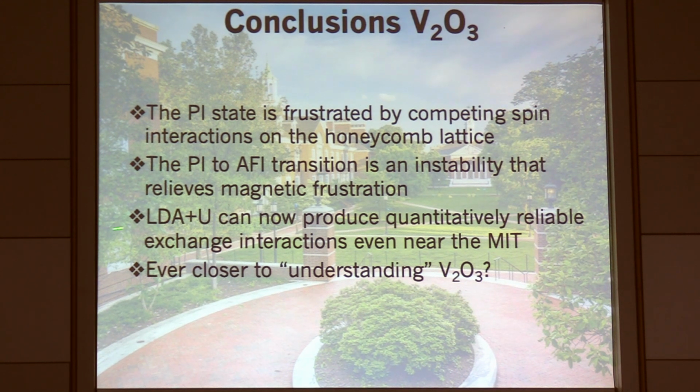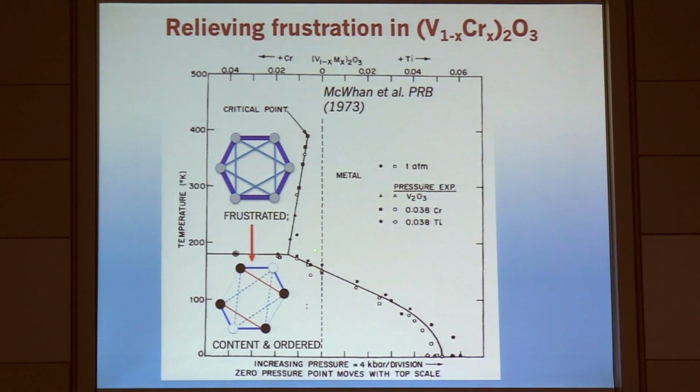And I think the message that comes from this regarding the Mott metal-insulator transition is that this may be found to come together with magnetic frustration, in the sense that in order to have this exposed Mott metal-insulator transition line, you have to do something to really suppress the long-range ordered magnetism. And in this case, this occurs because of the frustrated nature of the interactions on the paramagnetic insulating state.